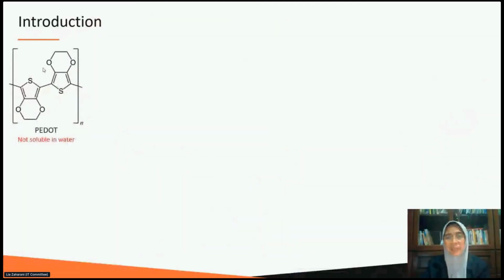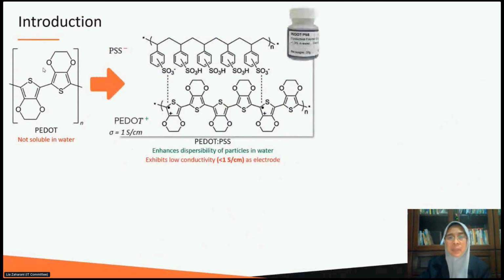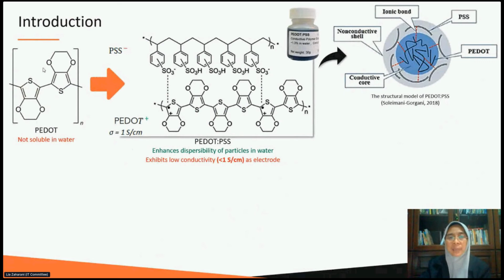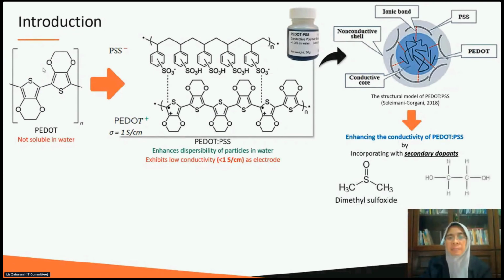In PEDOT:PSS, the PEDOT is a conductive p-type polymer that is not soluble in polar solvents such as water. Therefore, it is doped with PSS, which is an ionic conductor, to provide a stable, easy to process, deep blue water-based PEDOT:PSS dispersion. The PSS in the complex functions as a counter ion for the cationic conductive PEDOT. Although the addition of the PSS brings enhanced processability, this comes at the expense of decreased electrical conductivity.